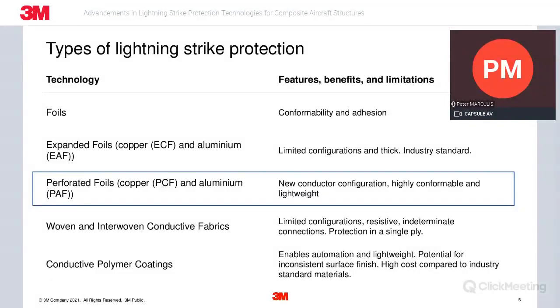Expanded aluminum foils are basically materials cut from continuous foil by putting slots into them and then stretching the foil to create this expanded foil. We at 3M, with some of our partners, have been looking at perforated foils for the last few years. This technique involves cutting specific pattern designs that are optimized to provide additional performance, which we'll cover in the next section. Less common, but still used a little bit in our field, are woven and interwoven conductive materials. The conductive fibers are woven in the outer layer of the fabric that goes onto the structure. Typically less effective, but maybe more efficient to put on the aircraft during its build.